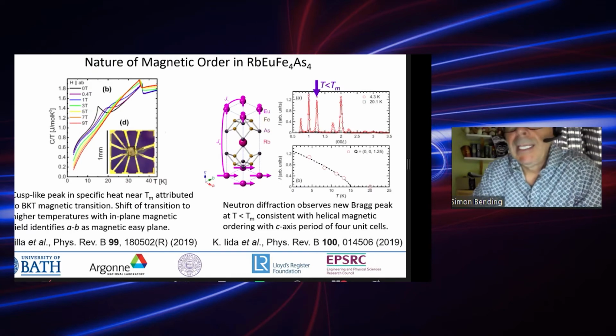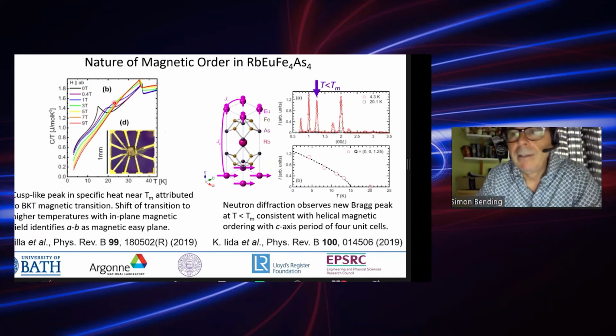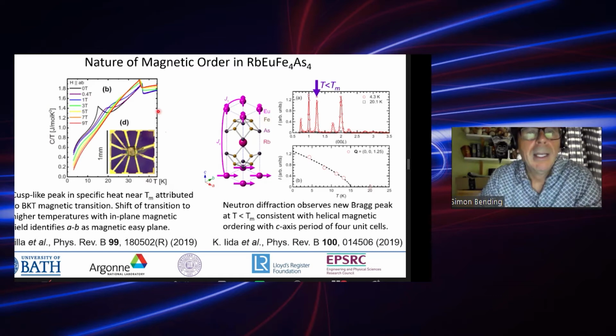Trying then to understand the magnetic properties of this material, we look first at these heat capacity data from Villa et al., which is published in this paper. So the heat capacity shows what you would expect, this normal jump here at Tc, which is the characteristic jump you see for a conventional superconductor. But then interestingly, it shows this second cusp-like feature here, which is the signature again, as we saw in the susceptibility, of the 2D BKT-like magnetic transition.